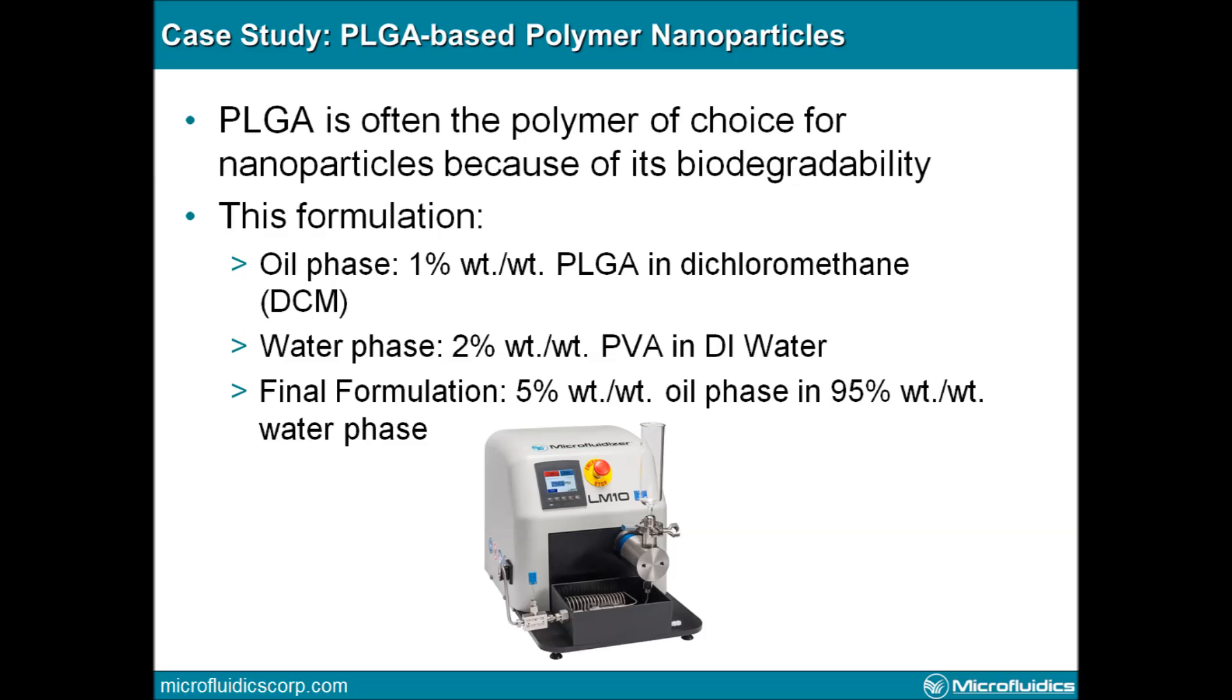The formulation we will be processing today is a 5% weight-by-weight oil phase in a 95% weight-by-weight water phase. The oil phase is 1% PLGA in dichloromethane and the water phase is 2% PVA in deionized water.